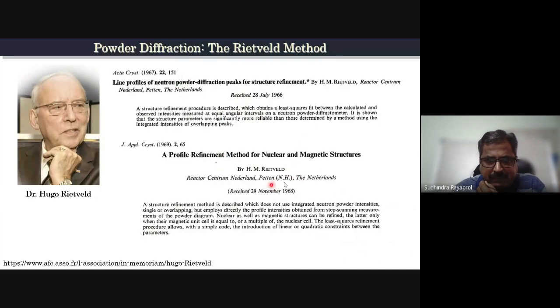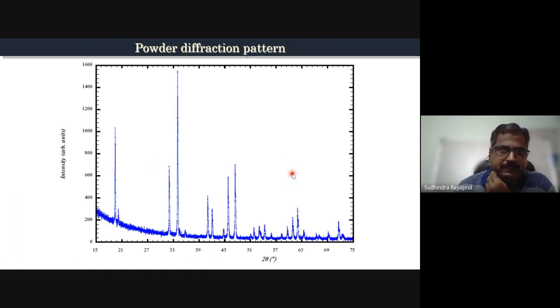So with the help of these initial papers, the Rietveld method was established for powder diffraction, and instead of using a high intensity peak or a choice of peaks, the full profile was used, and hence the program FullProf was coined for full profile. The full profile refinement method was actually started for nuclear or magnetic structures, basically using neutron diffraction. The application of this method to X-ray powder diffraction by Young et al. actually increased the reach of the Rietveld method as we know it today. Initially there were very few papers using the Rietveld method, but once it started being applied to X-ray powder diffraction data, the usage jumped like anything.